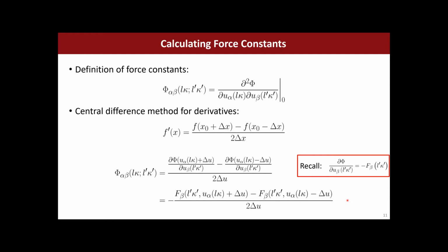And how can we determine these forces? Using density functional theory. Density functional theory is pretty good at calculating forces. So at the end of the day, we need to use DFT on structures where an atom has been displaced, measure the forces, get the force constants, and from that get the dynamical matrix.